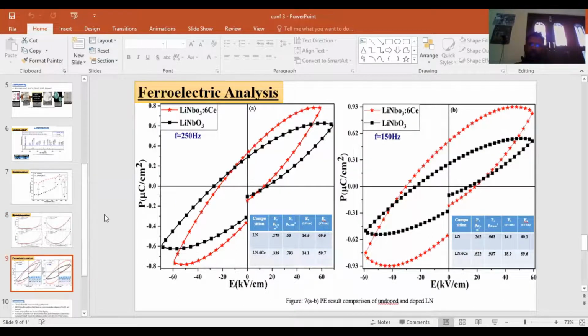I also performed the ferroelectric analysis, and I can say that lithium niobate, both doped and undoped, has ferroelectric nature. And in my research work, there is a good ferroelectric nature as compared to the literature survey. In the literature survey, the polarization value was approximately 0.25 microcoulomb per centimeter square when the applied electrical field was 4.5 kilovolt per centimeter.